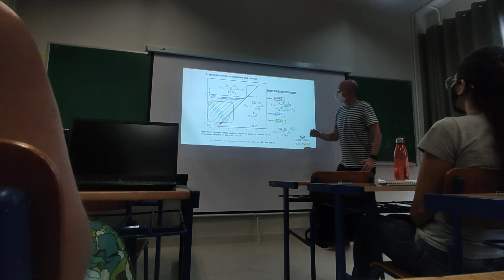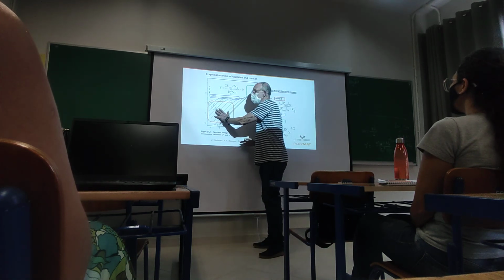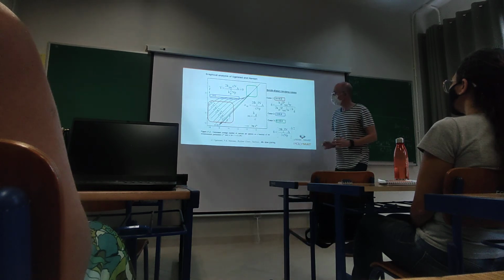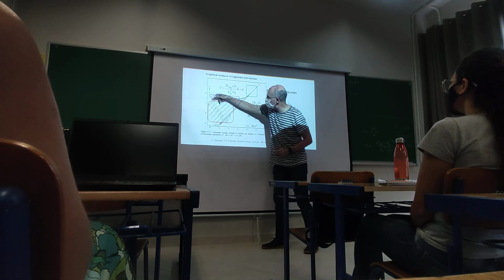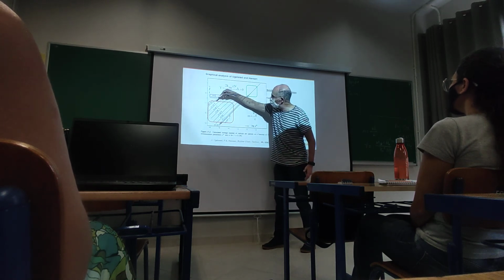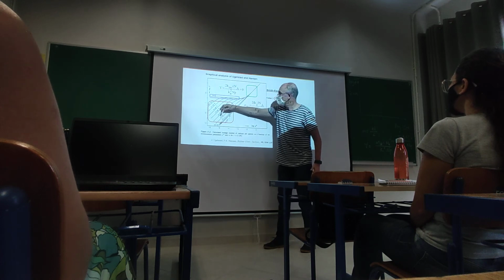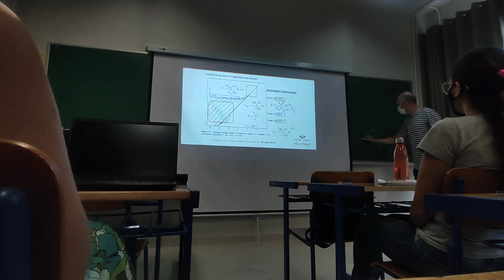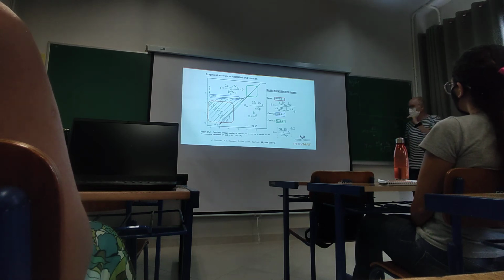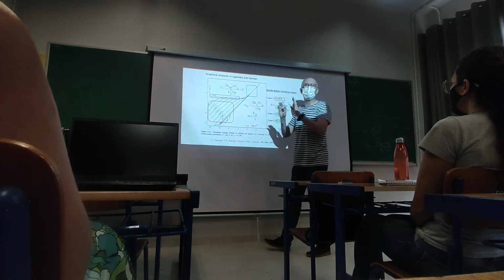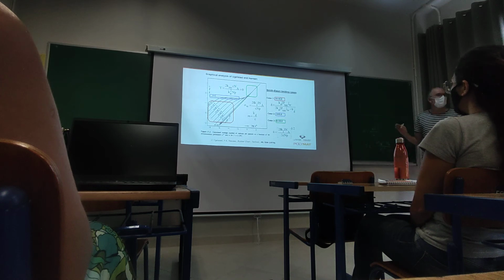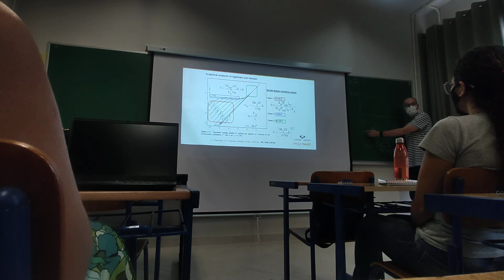Okay? So, if we take this area first, the area in red, what we see is that different values of N increasing, this is 10 to the minus 6, 10 to the minus 5, 10 to the 2. So N is this. If N is lower than 1, when N is 0, which is this line, means that we don't have exit of radicals. KD is negligible with respect to C, so N is 0. Okay?